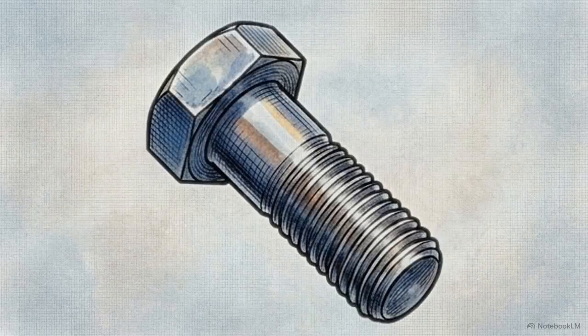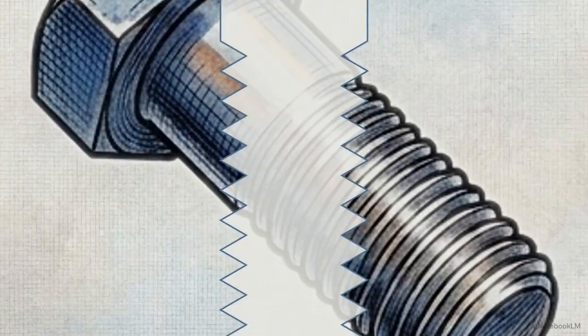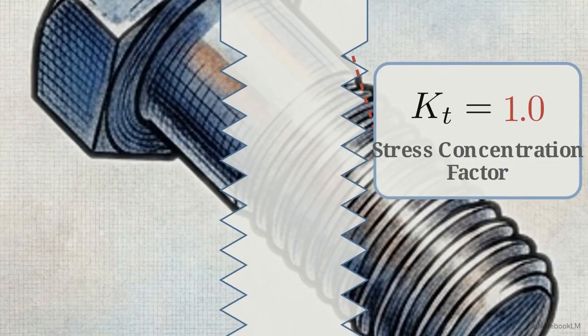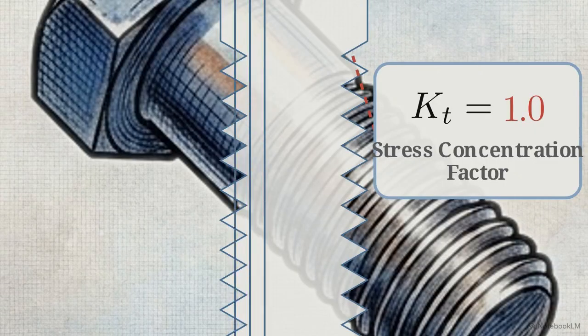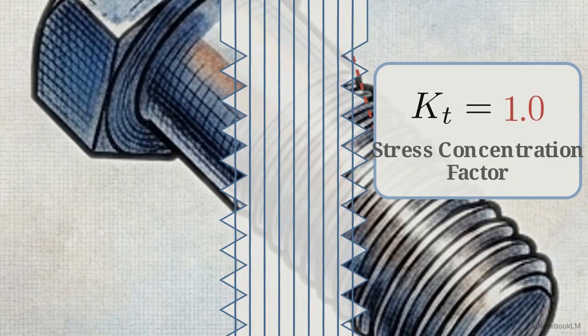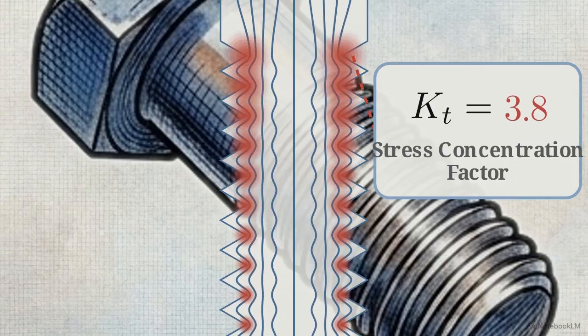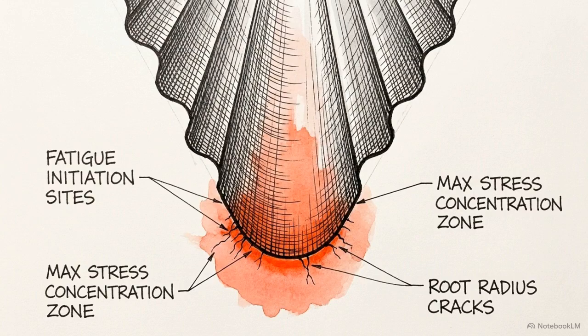This multi-point initiation is driven by the stress concentration factor, or KT. This is a geometric multiplier. When tension flows through a part, sharp notches like bolt threads trap and drastically spike the localized force. The sheer density of ratchet marks proves that high stress concentrations across the entire thread root triggered simultaneous fatigue initiation.